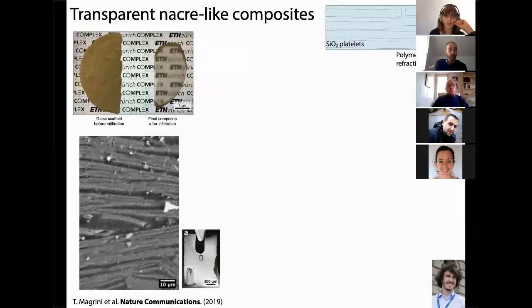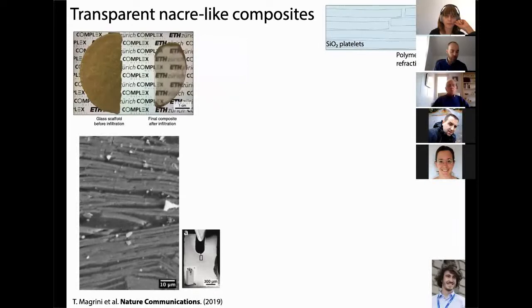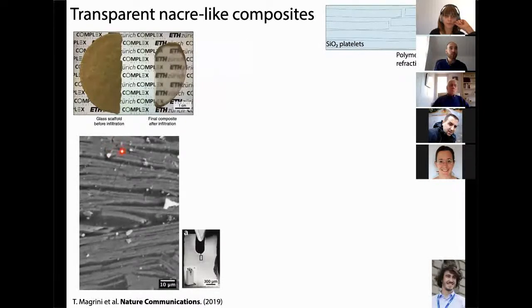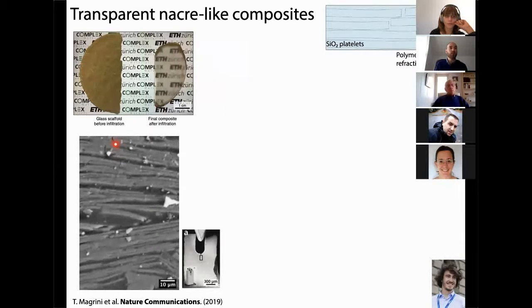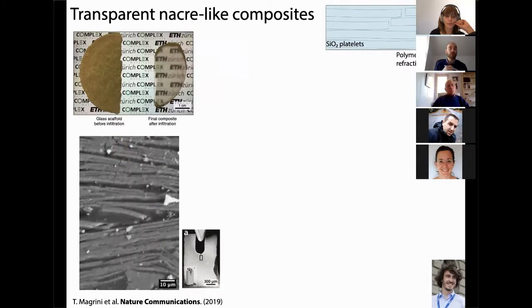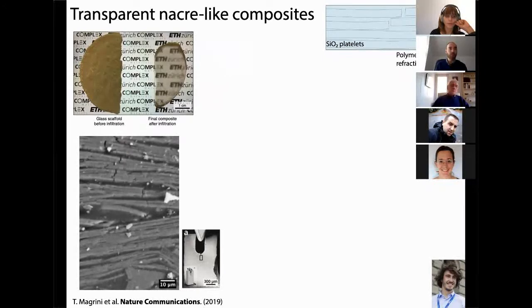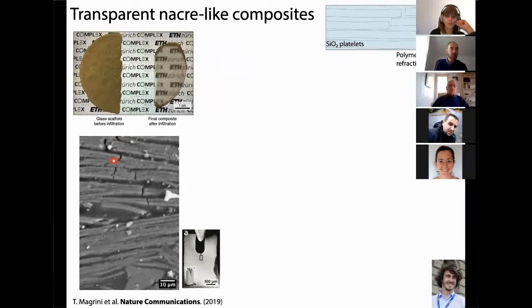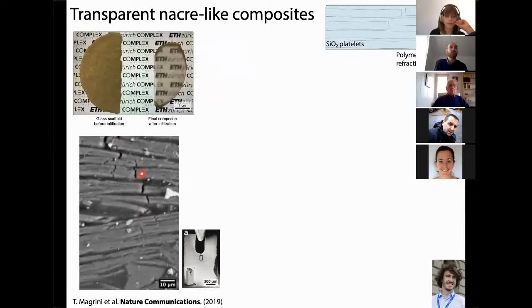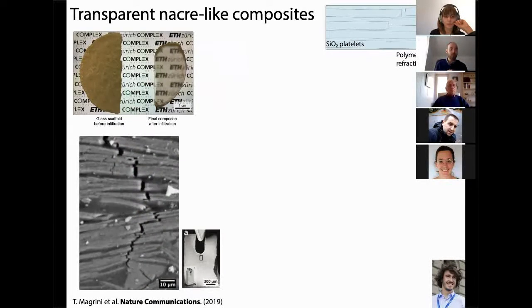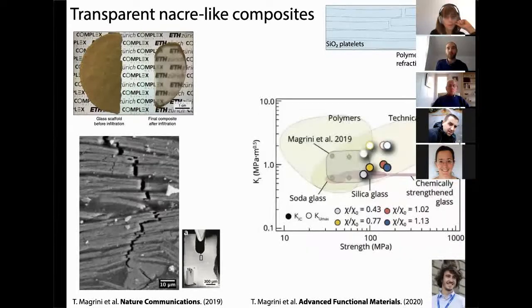So first, just to say we can actually make these transparent, but something we've also upgraded is our setup to look at fracture. And you can see here an SEM in situ test, where we open a crack, and you can see we use that to observe how the microstructure interacts with this crack and what mechanisms happen. So you can see we have a bit of deflection, right? But what is most interesting, I think, is that we can see this bridging polymer here and here that is stopping the crack from opening. And so we think that one of the main mechanisms of reinforcement in this type of composition is actually polymer bridging, as in technical composites.